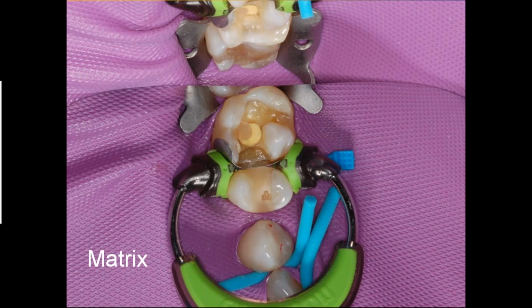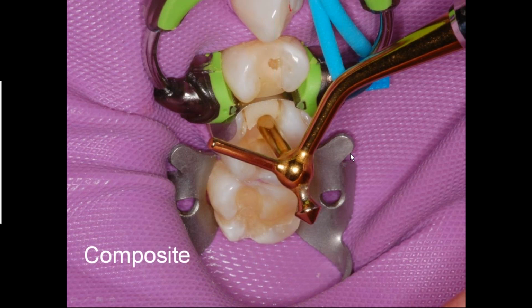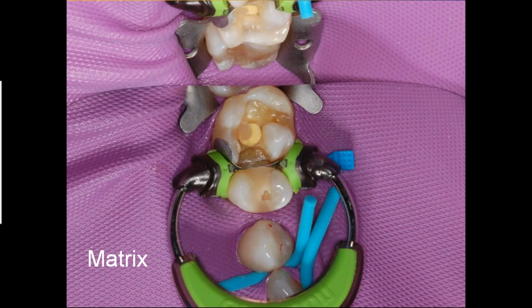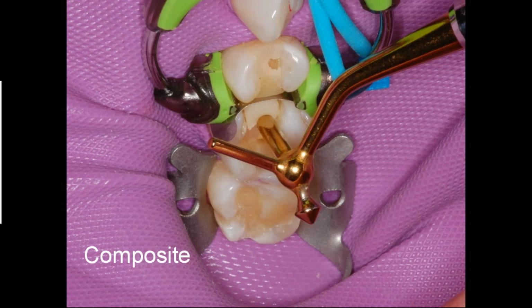And now we're going to go ahead and we place our matrix in there. They're about 1/1000th of an inch thick, and you'll see it has a special non-stick surface on there, which was invented by Garrison. And then you can see our wedge which was placed right there. Now we placed on our ring. Go back one there. Went forward on me. We placed our ring on there, which also spreads the teeth apart a little bit more. So now we have really a tenacious grab onto that matrix, and we separated the teeth.